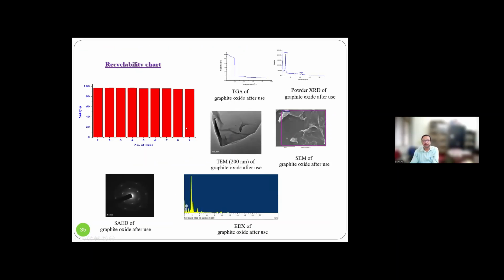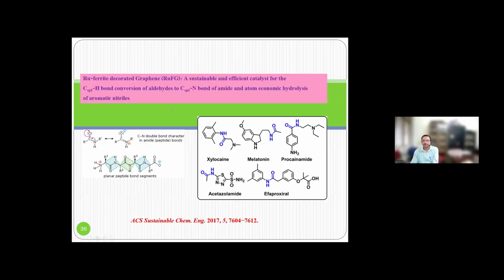Then we check the reusability, same thing in 9 runs. We check the morphology of the reused catalyst. It remains the same. Next, what we did actually, we dope ruthenium ferrite on the surface of graphene for the synthesis of amide bond.